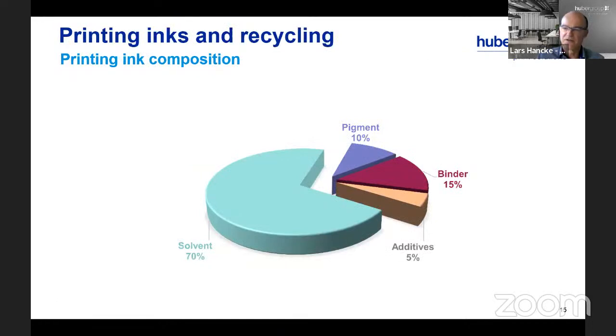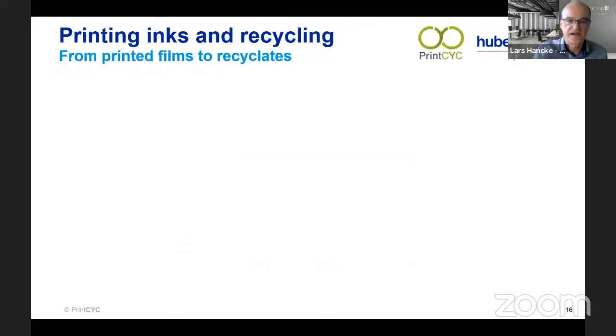And to understand what we have done, a brief look at printing ink composition, just in a nutshell. We are looking at solvent-based inks. Of course, they have a lot of solvent, and after the printing is done, the solvent is gone, and then we are left mainly with two components, the pigment, giving the color, and the binder, which makes sure that we can anchor the pigment to the printed film. And we have to understand that during the recycling process, which is basically an extrusion process, the printed packaging has to survive temperatures around 240 to 250 degrees Celsius, so very high, at least in ink chemistry terms. This is a very high temperature, and we need to understand what really happens with the ink when it has to suffer these high temperatures. And this is exactly what we have done.